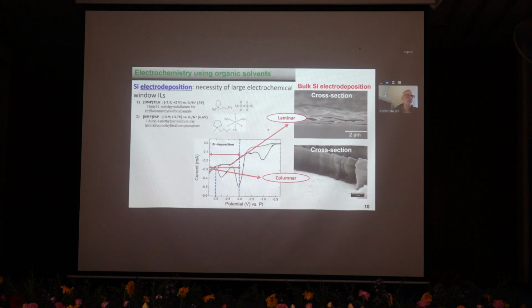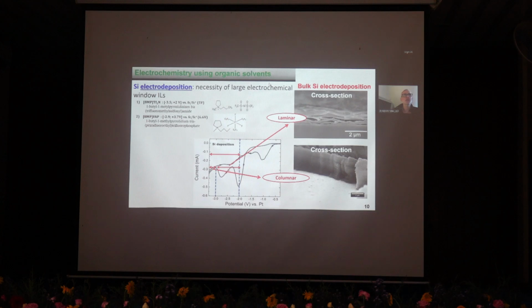Traditionally, silicon is deposited using vacuum methods like CVD or PVD at high temperature, often using catalysts like gold droplets, for instance. However, electrochemistry in carefully selected ionic liquid also allows silicon deposition at room temperature. Here we have a CV diagram, the current versus potential, using silicon tetrachloride as a precursor. We see a two-step process, first the reduction of silicon 4+ to silicon 2+, and then the production of silicon. Water would be limited versus platinum at -1 volt, so here we would not be able to reduce such ions in water, of course.